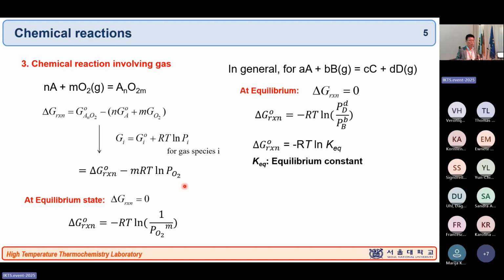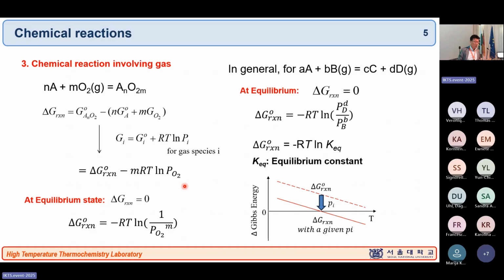But now, by changing the oxygen partial pressure, you can control the chemical reaction. You can make it a forward reaction or a backward reaction. So for example, like this, the Gibbs energy here. If you're considering only the pure standard state Gibbs energy, let's say it's like this. But by changing your partial pressure, now you can bring it down or bring it up, whatever you like.